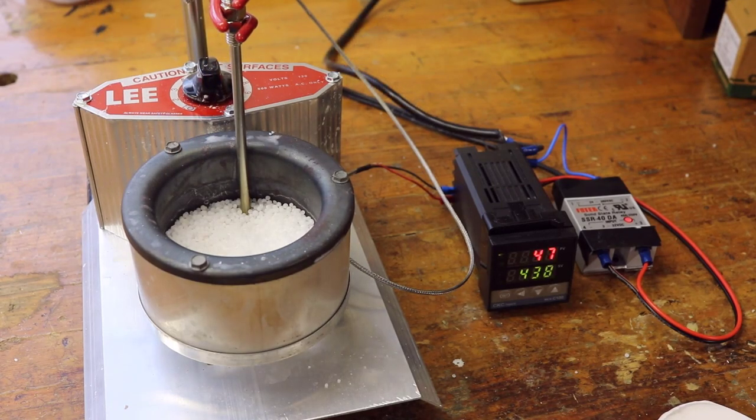Okay, now we have power applied. That'll come up to 438 degrees Celsius, not Fahrenheit. This is about 820 degrees F, which is a good place to operate. And this will melt down and it will be clear as water, and then we'll anneal some brass.